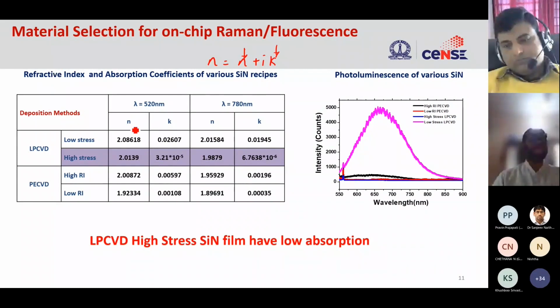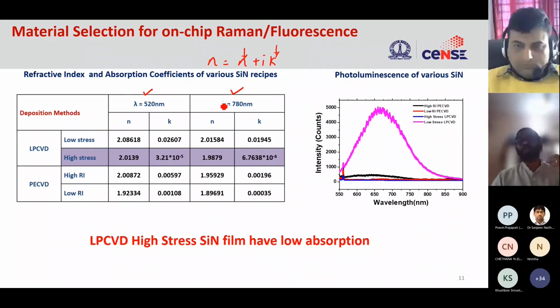We measure this N and K using ellipsometry. And we measure this N and K at two different wavelengths, 520 and 780 nanometers. Some of you might have already guessed why 520 and 780, because these are interesting wavelengths to do spectroscopy as an application. So you can do Raman spectroscopy at these wavelengths. Since it is a silicon compound, you want to make sure that it is not silicon rich, because silicon absorbs visible wavelengths. So you want to make sure the composition is right.